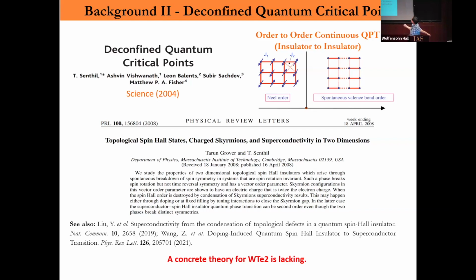It was initially developed in these spin models where you have, this is Néel order on the square lattice, and you have another, valence bond order, and the theory tries to put these two orders together with a continuous transition. Of course, this is not our case because both sides are insulating. It's only describing a spin system.